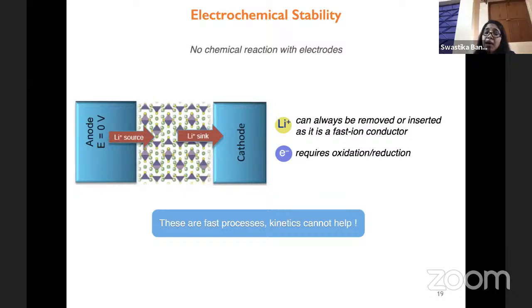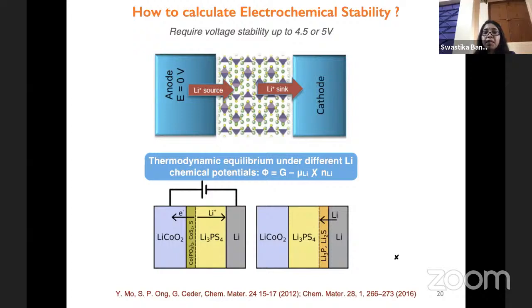So we need to understand the stable electrochemical window, which will not allow such insertion or extraction of elements like lithium ion. We want to define that quantity, the electrochemical stability window, where we can operate without any kind of reaction or exchange of lithium at the interface. So how do we calculate such an electrochemical stability window? We can construct the thermodynamic phase diagram, the thermodynamic equilibrium under different electrochemical potentials for lithium, and we can study what the stable products at the interface are.